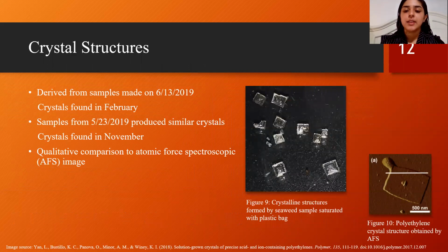In figure 9, you will see what my crystal structures actually resulted as. Just to provide some sort of a qualitative comparison, I found an image of an atomic force spectroscopy photo of a polyethylene crystal. The literature actually describes a sort of rectangular growth in which the length and width grow in different magnitudes, which was also exemplified by my own crystal structures.